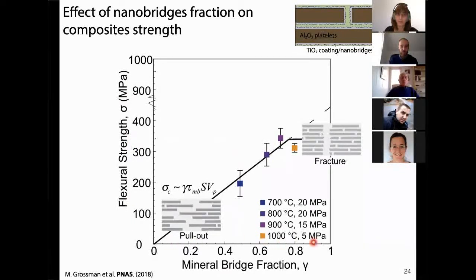Now, what was really interesting is we found that if you look at the flexural strength as a function of this mineral bridge fraction, for a long time the trend is actually quite linear. And it seems to tell us that it just follows a normal shear-lag-like model. So the stronger the interface, the stronger the composite in this case. And at some point, when we have too high a bridging fraction, we start breaking some platelets. So we start seeing platelet failure. The interface is so strong that we start breaking these platelets at the end.